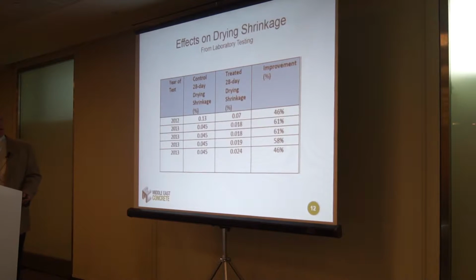Effects on drying shrinkage from my laboratory and others show a range. 2012 to 2013 is when we did this testing. From 46% to 61% or so. This is the post-applied colloidal nanosilica. And this again is not just the UTC laboratory. There were a few of these studies that were done at Middle Tennessee State concurrently.